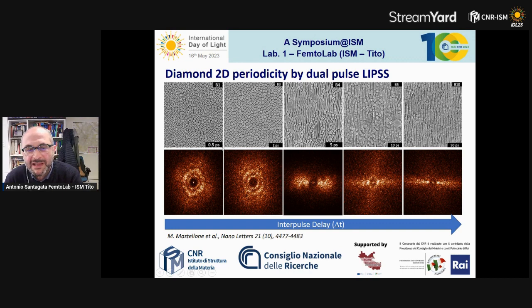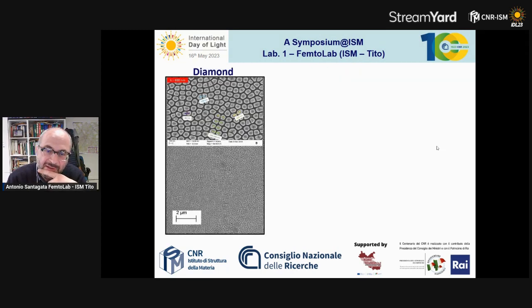In this case, we see that we can have a structured surface with very short delays, and we lose that two-dimensional nanostructure with longer delays. It means that it's a different way, of course, of the interaction between the first and the second laser beam because of the excitation that is induced by the first and interacting with the second incoming laser beam. So, for example, in diamond, we can improve the optical properties, the absorbance properties, just by varying the delays between the two laser pulses and reach even very short spatial periods, which are roughly in the range of 100 nanometers up to 80 nanometers.